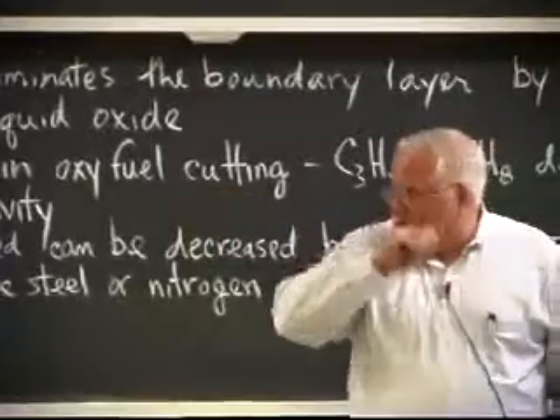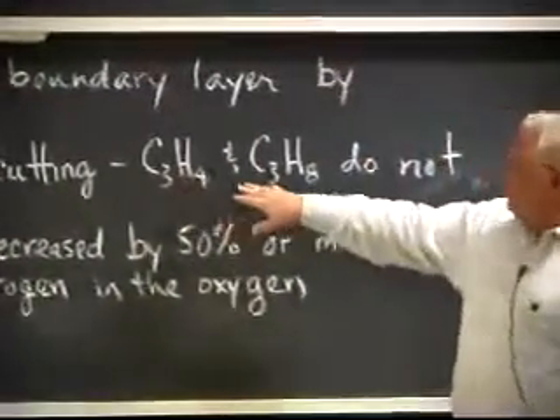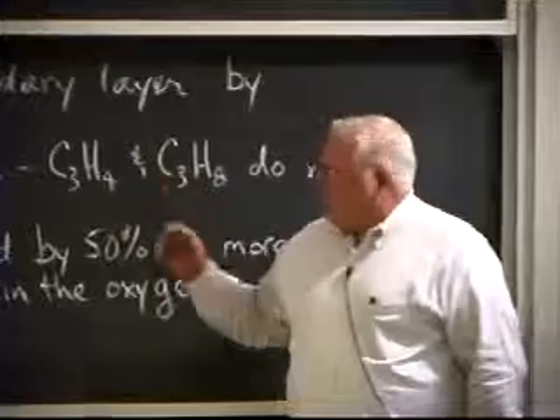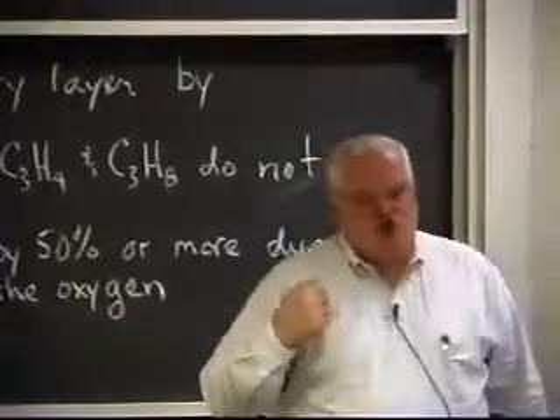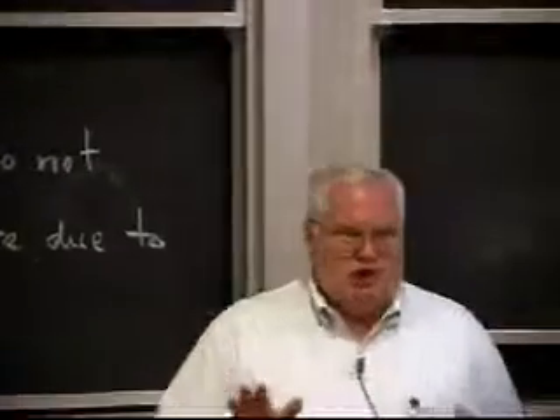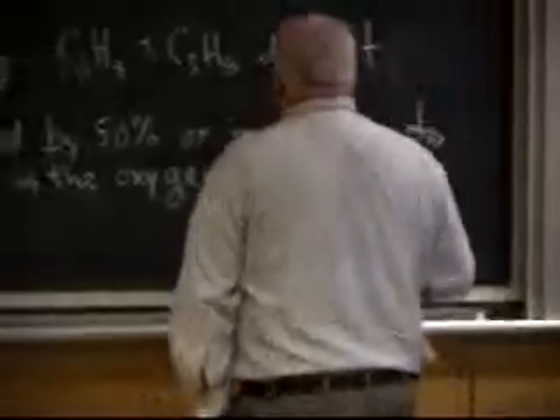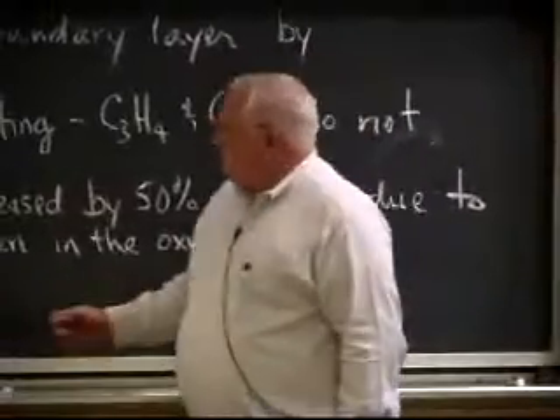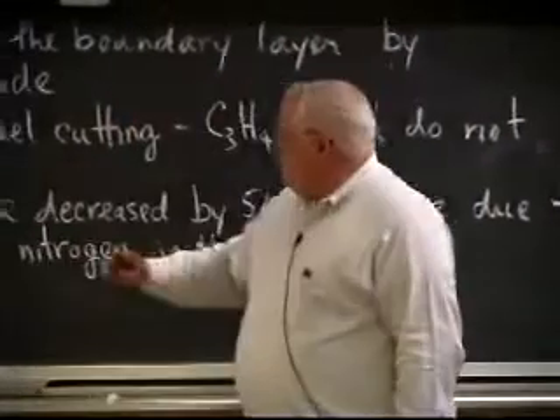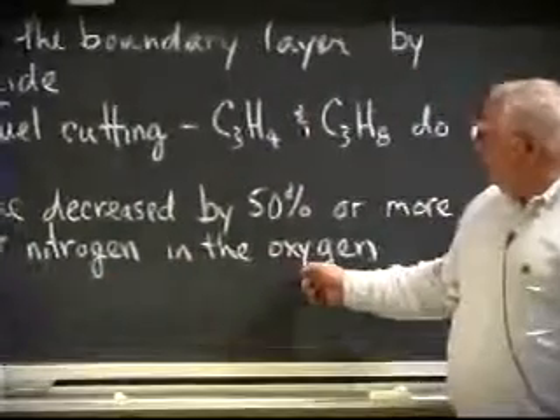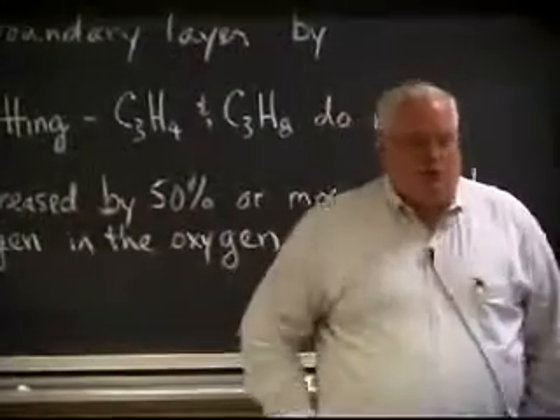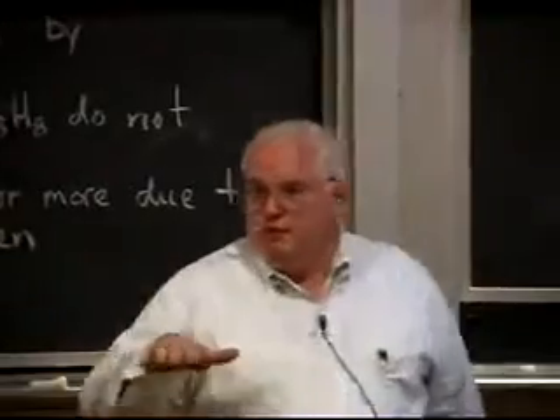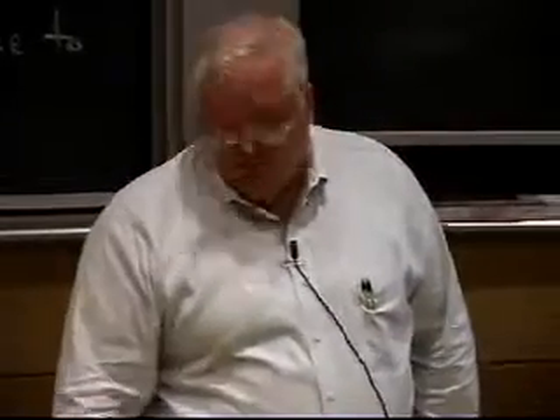Iron is the fuel in oxy-fuel cutting. It turns out it really doesn't matter whether you use MAP gas or propane, because those just allow you to start the process. Once the process is started, you can actually turn off those pilot flames because it's the oxygen that's burning the iron. And we also said that if you have impurities such as carbon in the steel, which forms carbon monoxide during the burning process, or nitrogen in the oxygen, you can lose up to 50% of your cutting speed because you will form a boundary layer, and that essentially limits the rate at which oxygen can get to the fresh iron surface.